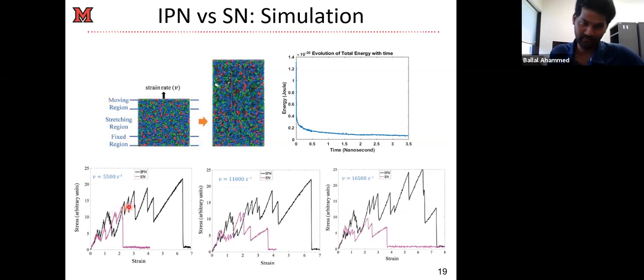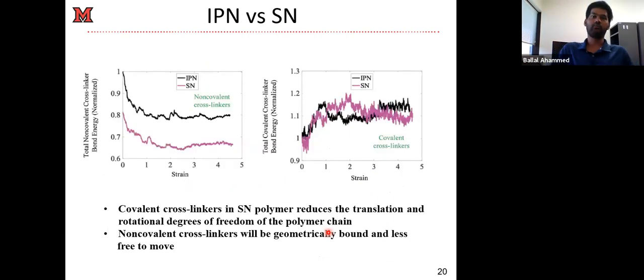Don't bother about the shape of the curve because it's very length and size dependent, and also we are using coarse-grained simulations. But in our case, we found that at the same strain rate, for the different strain rates, the IPN is outperforming the SN. So that's a good sign. That means that our model is good. It is able to capture what's happening inside, at least in terms of trend, it's okay. So that's not bad. So now we try to answer the question why the IPN outperforms the SN.